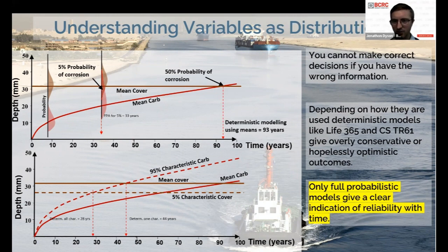And the long story short is that full probabilistic analysis is more reliable, it gives higher reliability, and it gives more accurate modeling to understand what your actual remaining service life of a structure is. And that might be remaining service life to time of initiation of reinforcement corrosion, or it might be factoring in the propagation period for reinforcement corrosion as well. So it might be modeling until the time that a concrete starts to spoil due to the corrosion of the reinforcement, for example.